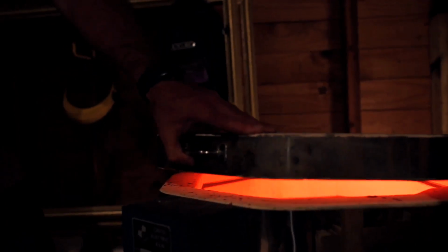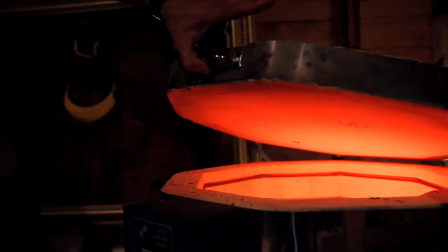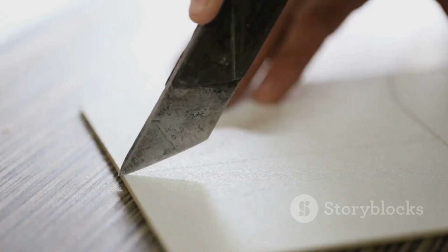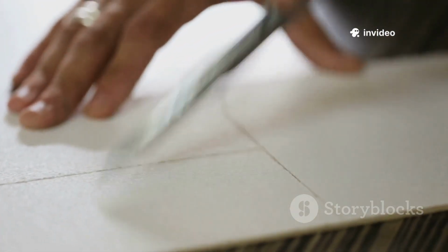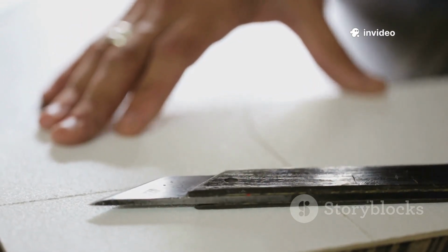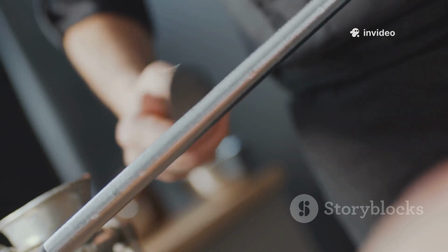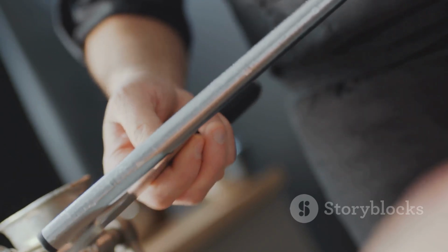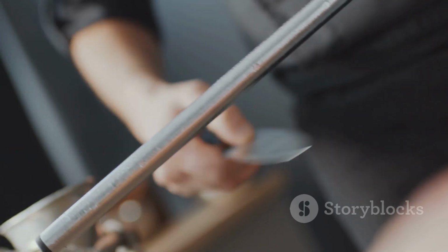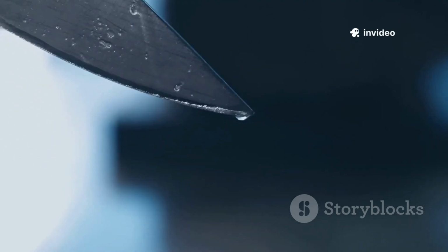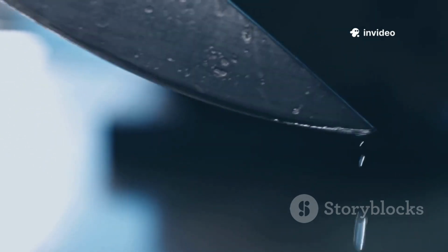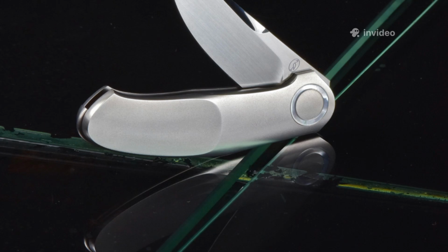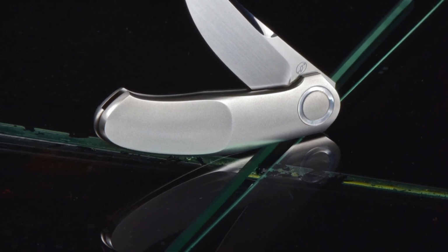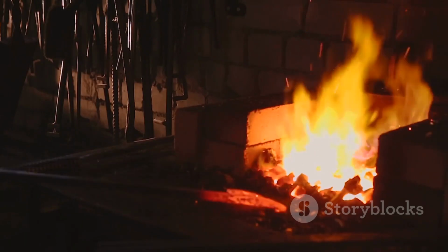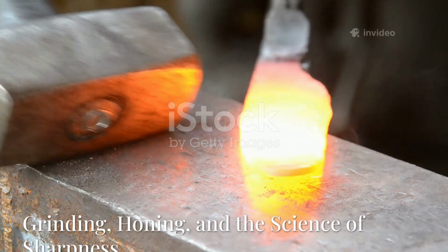The knife maker can control the final properties of the blade by carefully controlling the tempering temperature. A lower temperature results in a harder, more wear-resistant edge, perfect for a razor. A slightly higher temperature results in a tougher, more flexible blade, which is better for a heavy-duty chopping knife or a sword. This delicate balance between hardness, the ability to resist being scratched, and toughness, the ability to resist breaking, is the secret to a great blade. It's a scientific trade-off, engineered with fire and precision.